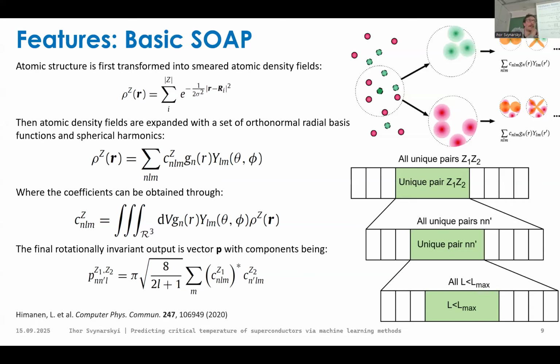I believe they should be the same because this SOAP is calculated just for one site, and then for the cell they would be averaged somehow, and if you just double your unit cell and then average it, it should be the same thing. But maybe the question is whether these functions are invariant with respect to translations. Exactly. These coefficients by themselves are not invariant. But this P should be invariant under rotations and some other transformations. So yes, they were trying to do something invariant. But it depends on the composition of this C. They are not, but this thing in common is invariant.